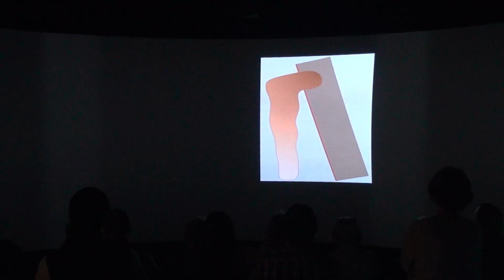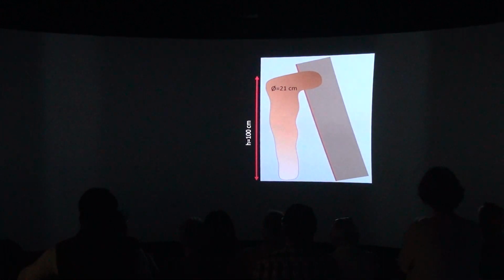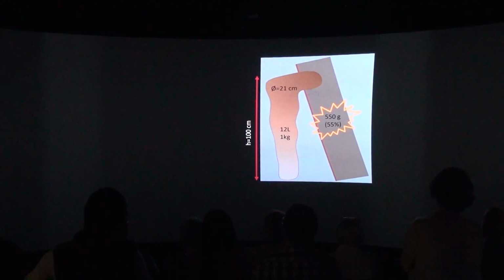How much iron do we need to create a natural rusticle? For example, the ones in the Titanic that are massive. For example, a 1 meter rusticle with 21 centimeters in diameter, 1 kilogram of mass, and 12 liters of volume, we only need 550 grams. The other things are oxygen for the oxides and how porous they are. So they are just fluffy, as you could see in the pictures when the ROVs passed next to them and they just poof.